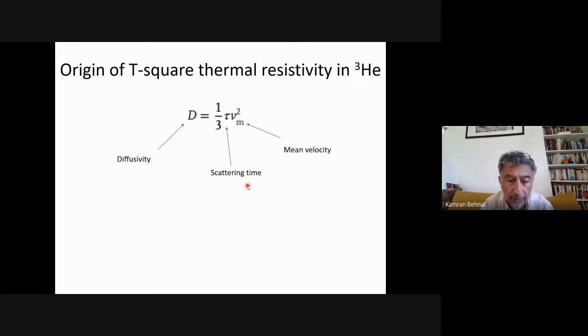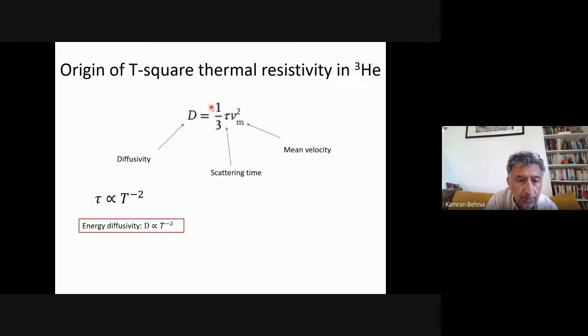They do not invoke two reservoirs. All fermions are similar in helium. There is no lattice. There is no place for umklapp. You have just normal scattering, and you have a T-square resistivity. How come? Well, as you know, the diffusivity in kinetic theory of gases is just proportional to the square of velocity. This is the mean velocity of your molecules or your particles. This is their scattering time. This prefactor depends on dimensionality, and this gives you a diffusivity. So this is true for thermal diffusivity. This is true for momentum diffusivity or viscosity.